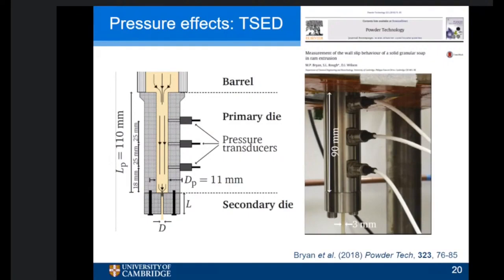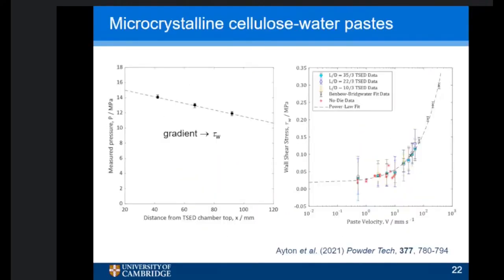Obviously, it can't be too sharp because then you're looking at an extensional system. So one of the things we have here is that we're quite happy with it being in a 1D system. And people have used conical systems as well because then you're capturing an evolution of velocity as well. So as long as the system isn't very pressure dependent, because the plot I showed you here showed a nice linear gradient. If the system is pressure dependent, well, then this is no longer straight, because the first point here is at a higher pressure than the point below, which means you then tend to get curvy lines, if I can put it that way.